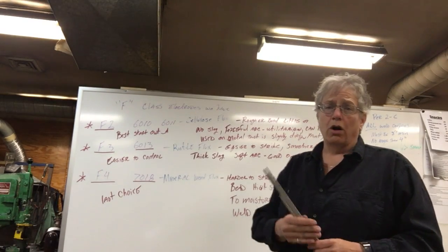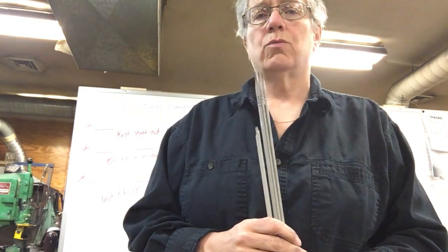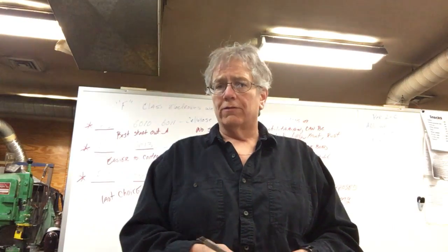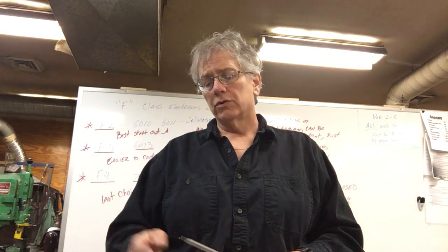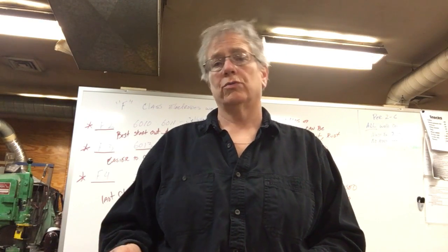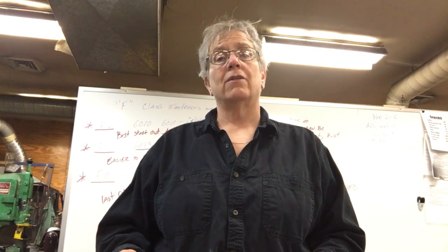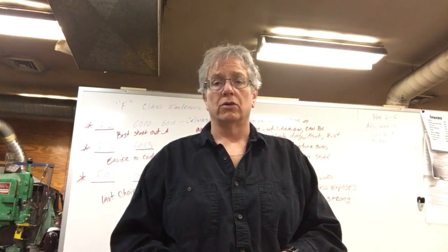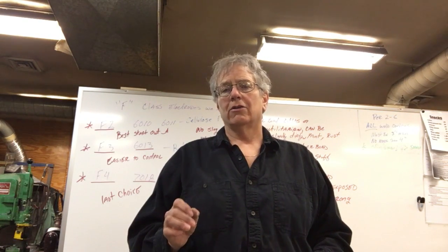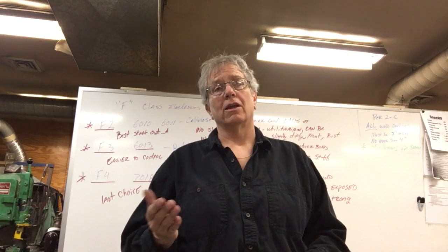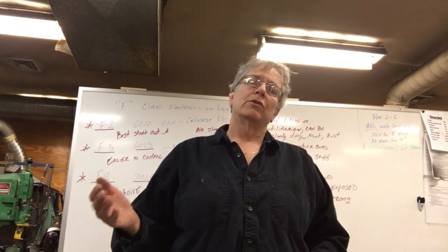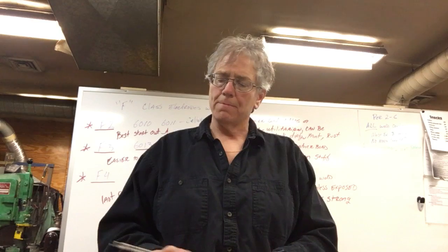If your amperage is wrong with 7018s, 8018s, 10018s, 7024s, any of those, your slag is going to be hard to come off. If it's too hot, you won't get your slag off. If it's too cold, you won't get your slag off. But with 7018, if you have too low an amperage and it's too cold, you're also going to have your electrode stick, okay? 7018 and 6011 are really good at sticking when your amperage is too cold. Don't get in the habit of running your electrodes too cold. If you do that, you're going to get poor penetration, which then results in a weaker weld, okay?